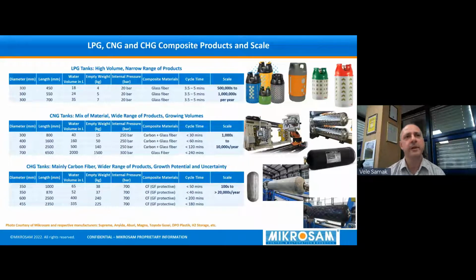You move from LPG to CNG. Now the issue is two types of material. Typically it's carbon fiber, some carbon fiber layers, some glass fiber layers, much higher pressure now, almost 10 times as much pressure, and also much bigger variation in products. So anything from 40 liters up to 500 liters in some configurations, to the 2,000 liter products that are out there in the market. So in this case, we're looking at thousands to tens of thousands of such products with varied cycle times ranging from half an hour to a couple hours or more.